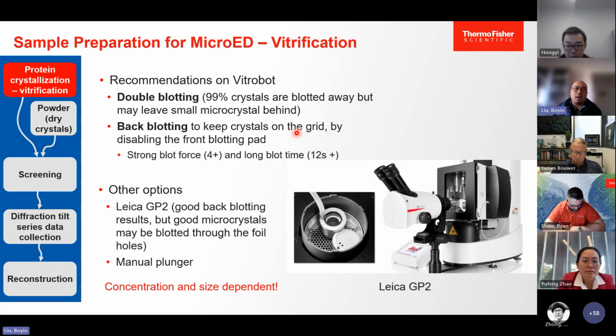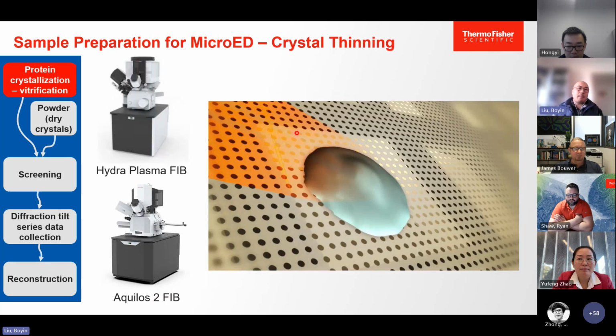And even with back blotting, some crystals still get stuck on the Teflon, so you still need to be careful. There are other options like the GP2, which is specialized in back blotting. It gives you better back blotting results, but some good microcrystals may be blotted through the foil holes from the back. So basically, both the Leica and the Vitrobot have pros and cons. It really depends on the concentration and size of your crystals, so we can't really give a clear recommendation about this. And so you have the cryo-FIB technique to make smaller crystals when your crystals are too big.